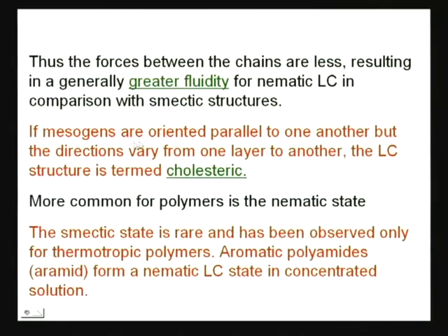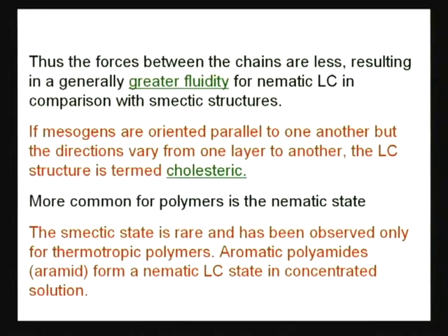If mesogens are oriented parallel to one another, but the directions vary from one layer to the another, then the liquid crystalline structure is termed as cholesteric, as I was telling. Suppose this is a plane of polymer molecules, where polymer molecules are aligned in this way, and mesogens are also aligned in this way. Now, a plane beneath this plane may contain again these polymers, where the mesogens, if they are not aligned in the same direction, will get different liquid crystalline behavior. So, if mesogens are oriented parallel to one another, but the directions vary from one layer to the another, the LC structure is termed cholesteric.